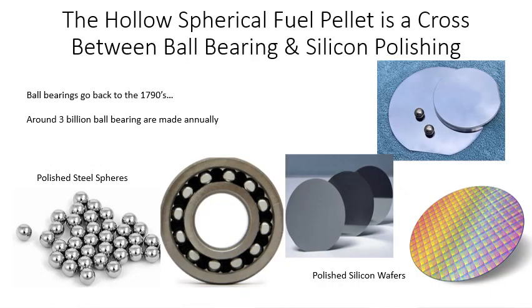To make this deuterium or tritium fuel pellet, instead of having flat discs, you've got to make almost a silicon ball bearing, a small silicon sphere. So you're kind of merging manufacturing techniques used for silicon computer chips with stainless steel or steel spheres or ball bearings. By merging these two mechanical processes together, you can form the first part in the fuel pellet for the fusion, inertial confinement fusion device.